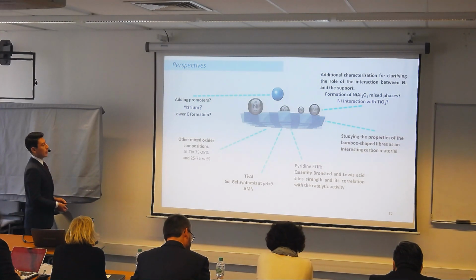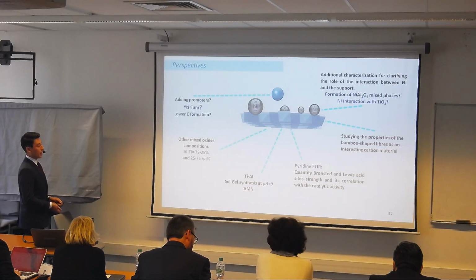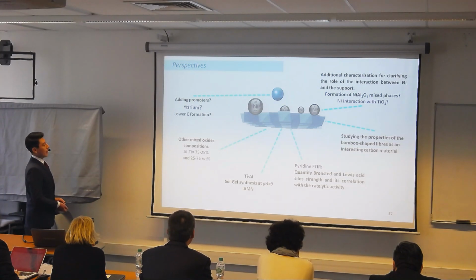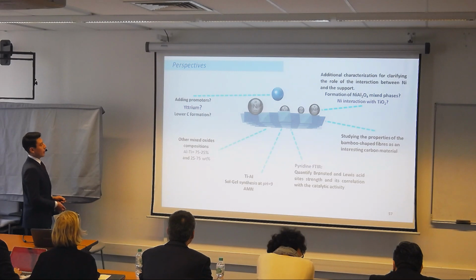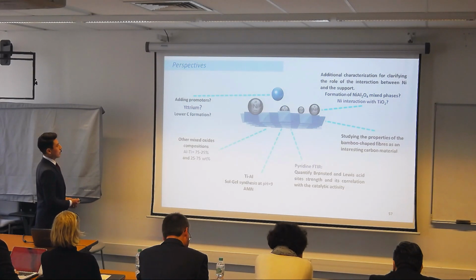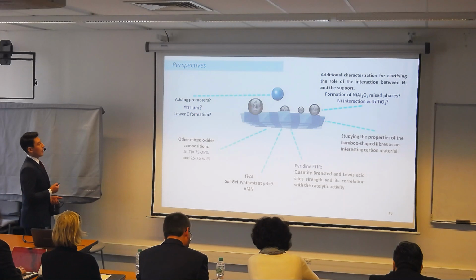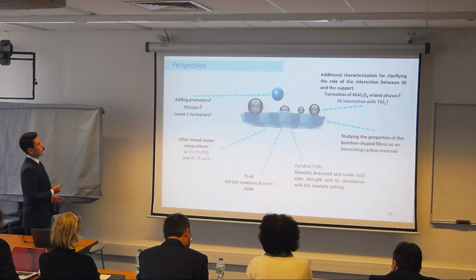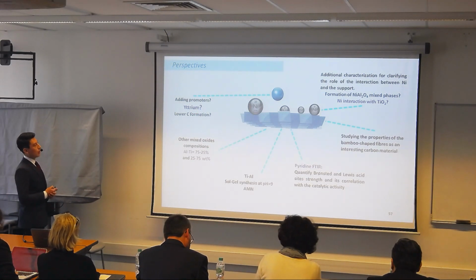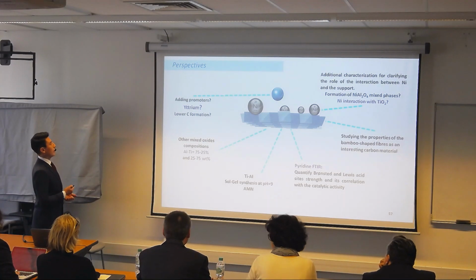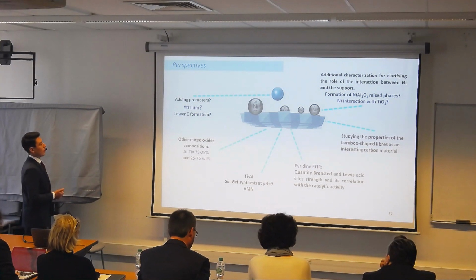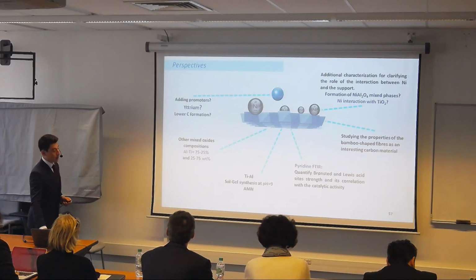I'm also proposing another support, titania-alumina, and we can prepare it at pH 9. As we see, this pH has the best results, and all the supports that we used in this thesis are 50-50. So I'm proposing here different compositions of this mixed oxide to see the behavior. About the carbon formation, I'm proposing the addition of another metal such as yttrium, as was reported to decrease the carbon formation.